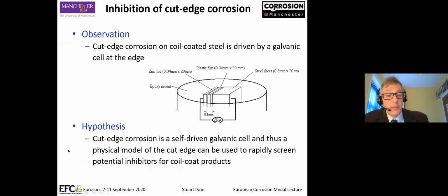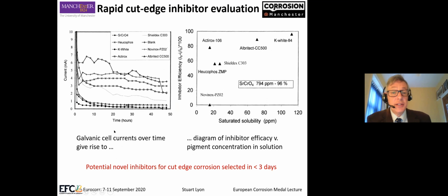And so our hypothesis is, because it's a self-driven galvanic cell, if we use a physical model of the cut edge by putting small bits of zinc or zinc alloy, separated electrically from the steel, at roughly the same aspect ratio for exposed area, we can rapidly screen potential inhibitors for coil coat products. And indeed, that's what happened. So, rapid cut-edge inhibitor evaluation.